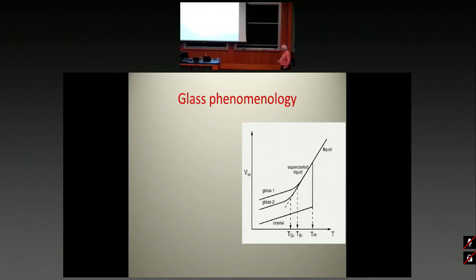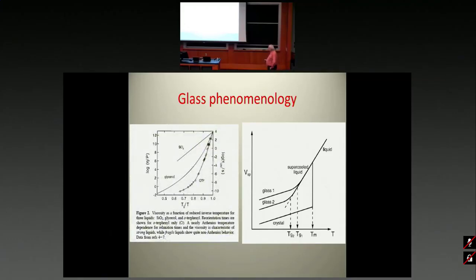Now, this point where it becomes so is known as the glass transition. But the glass transition is not a very well-defined transition for the problem. If you quench or if you go slower in this supercooled regime, you go deeper into the supercooled, and then you get a glass that is more stable. And there is a range at which you get these glasses, but the phenomenon that is of interest here is that the rate of increase of the viscosity is tremendous. Let's say on a small range in temperature, the viscosity that is measured here in poise can jump 12, 13, 14 orders of magnitude. So for every practical purpose, the material is a solid.